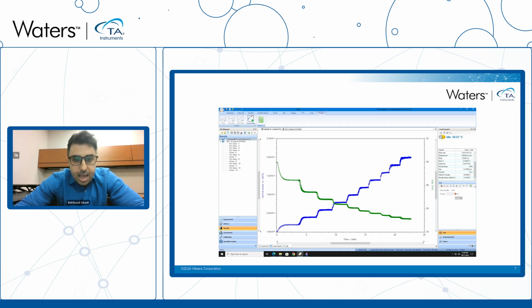The green one is the gap, the blue one is the normal force. So you have the reference gap, for example, as 30 millimeters. You put a normal force of 2 kilopascal, so you have a drop in the gap, and then you would have a kind of steady state. The gap does not reduce further, so you cannot compress the powder more.